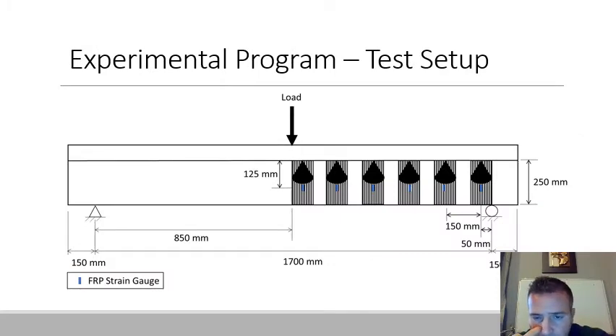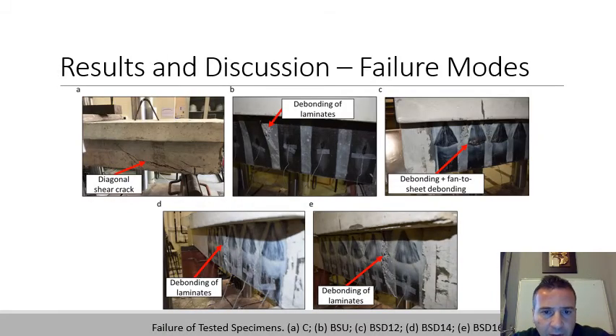So this is the experimental program again, and you are just strengthening one side of the beam and applying one load in the middle. We put an LVDT to measure the deflection of the specimen, so the recorded data will be the load and the midspan deflection. In addition, we put strain gauges in the middle of the strip to find the strains in the FRP sheets, and to see how much of the capacity of the CFRP U-wraps we utilize.